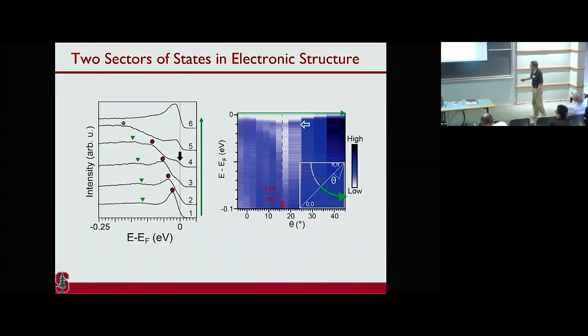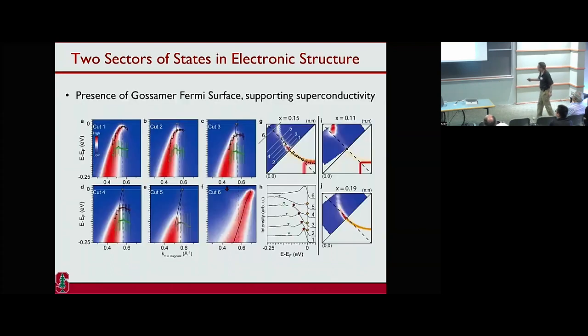So now you can see here, indeed, this is the normal state. Indeed, this feature inside actually becomes the superconducting feature. It's not the piece that gives you the large reconstructed Fermi surface. There were residual states that give you the superconductivity. Again, that's the data.